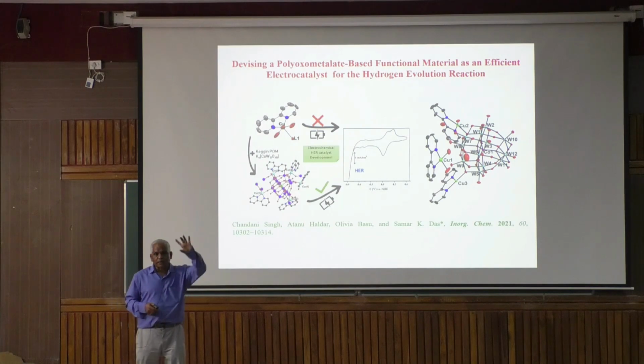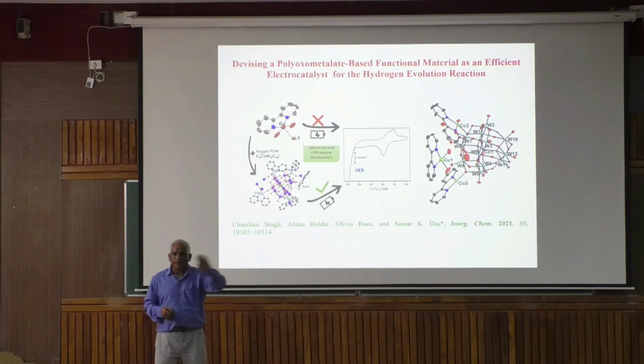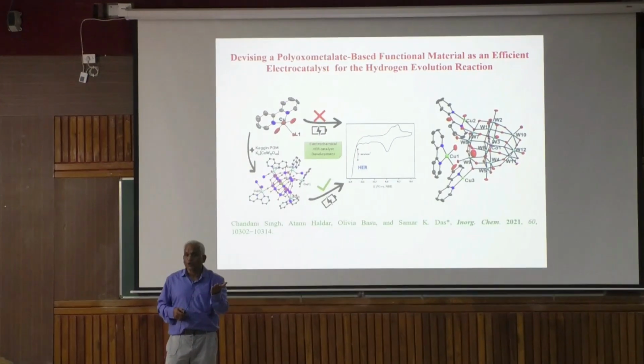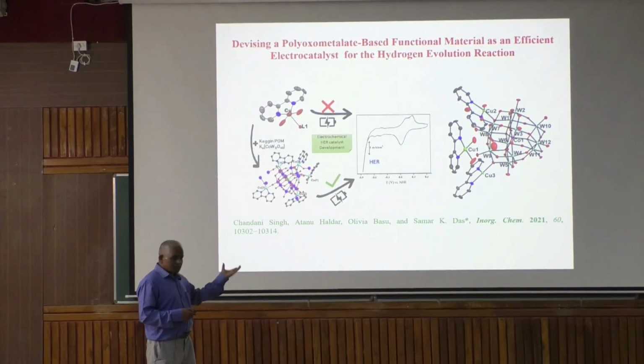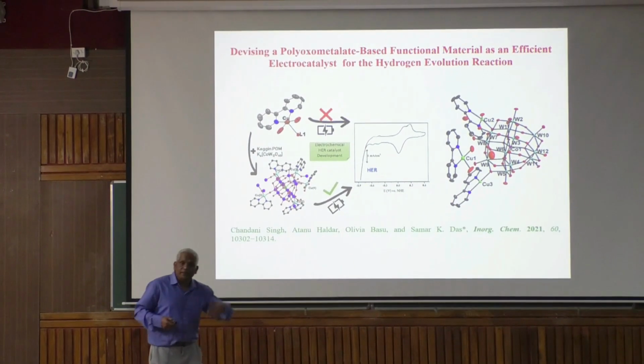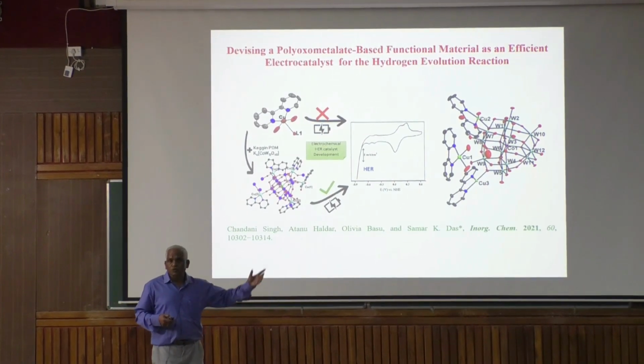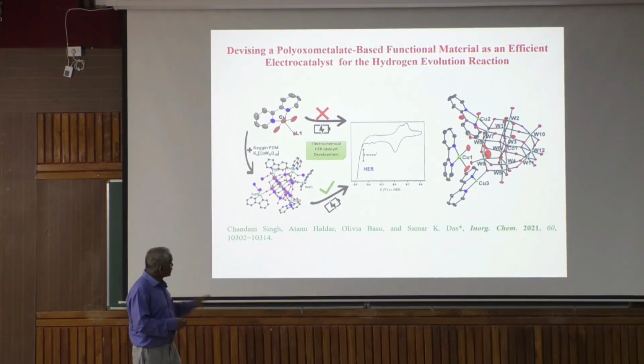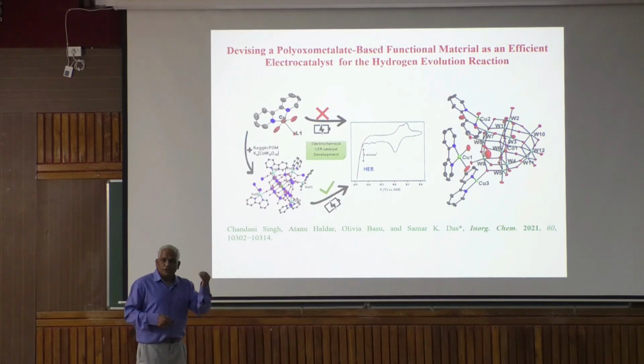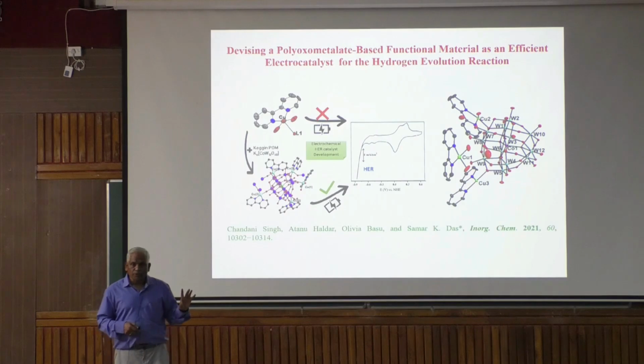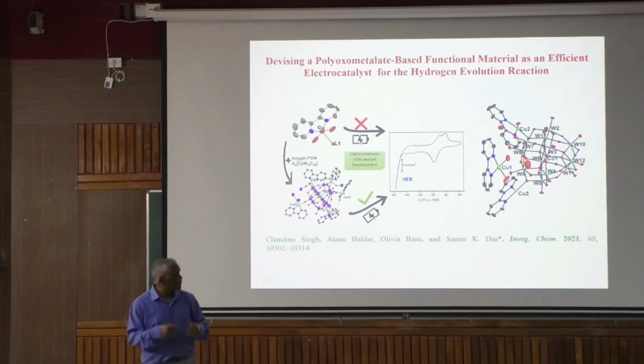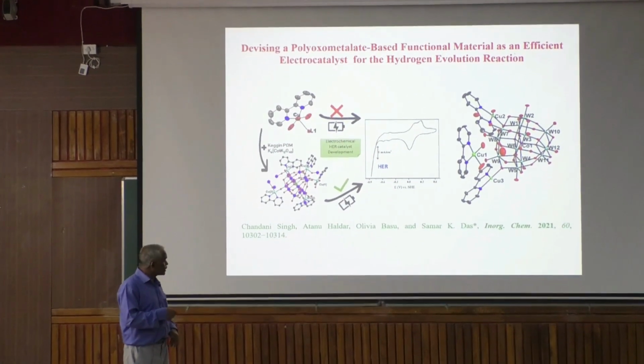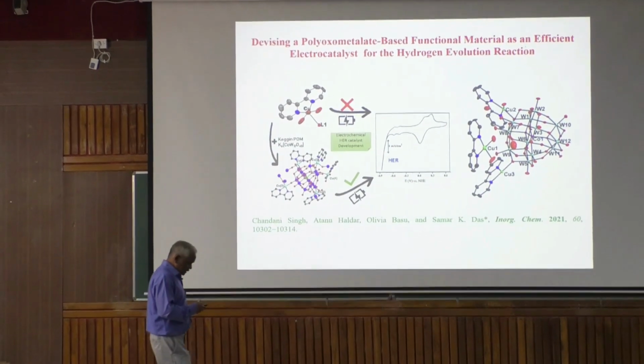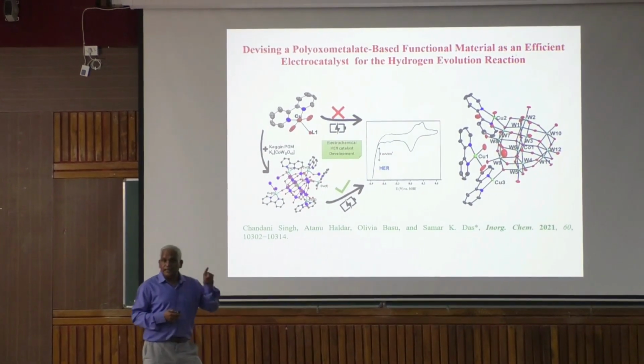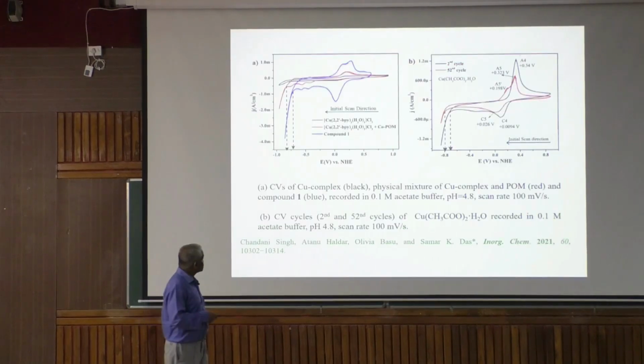After electrolysis, we checked that material and we found no elemental copper. Always we find copper 2 only. So copper 1 forms in a very unstable manner, very active, and immediately reduces the H plus, the proton, to hydrogen. That's why at any resting time, if you do XPS, everything, you get copper 2. So in a similar system, when you put in a coordinate covalent bond, you get continuous hydrogen evolution, a very stable catalyst. So interesting, the intrinsic nature of the metal makes this difference.